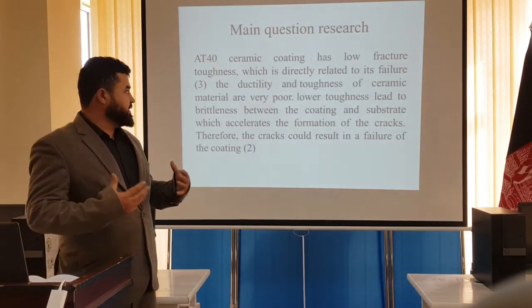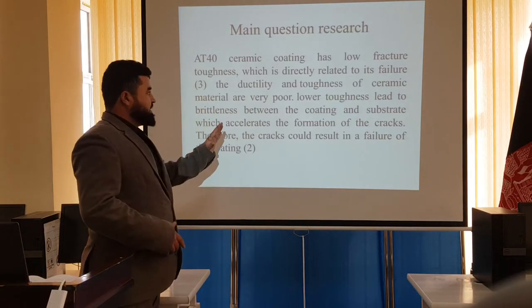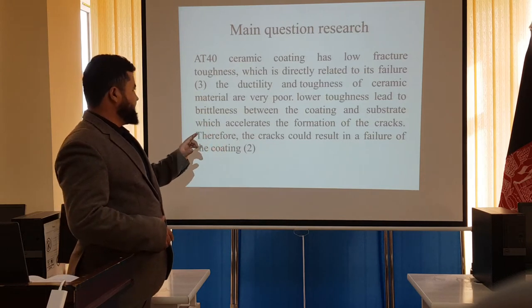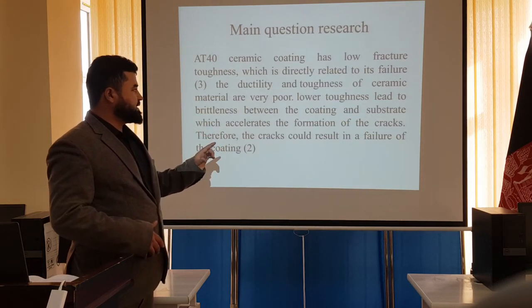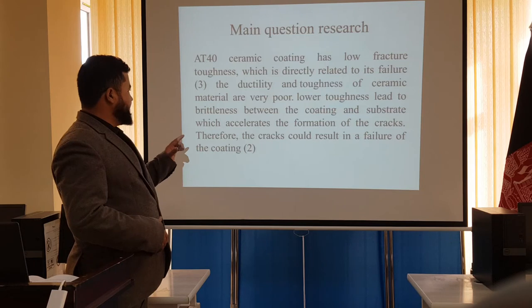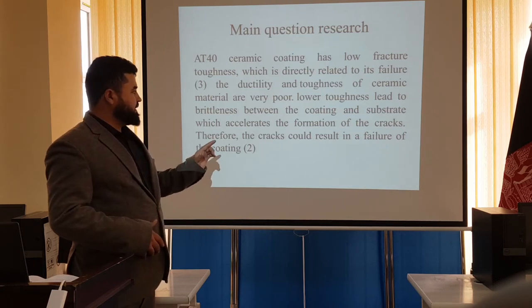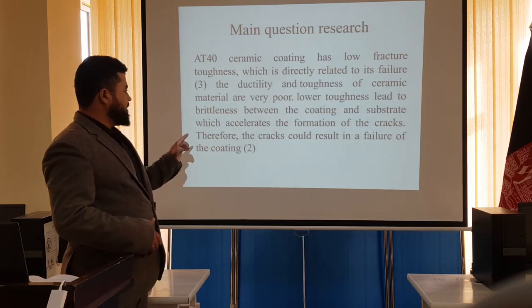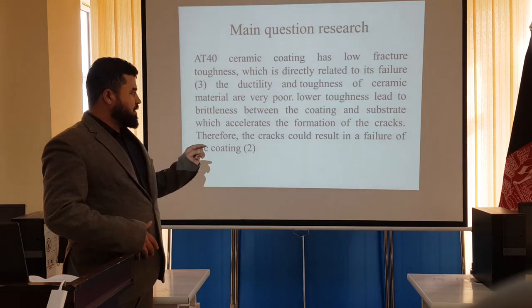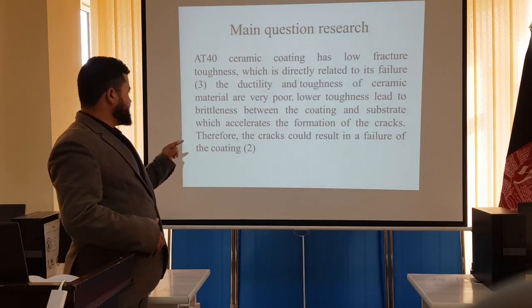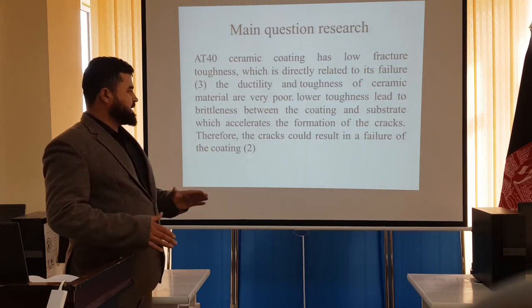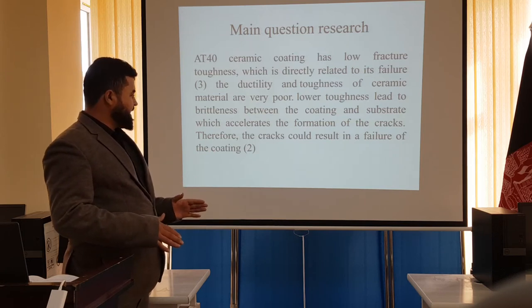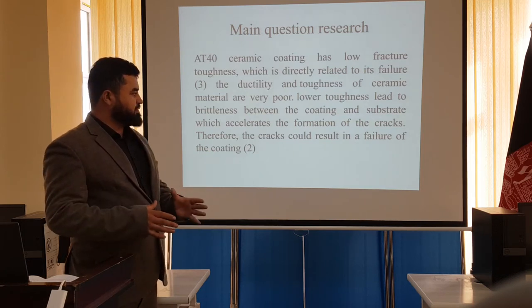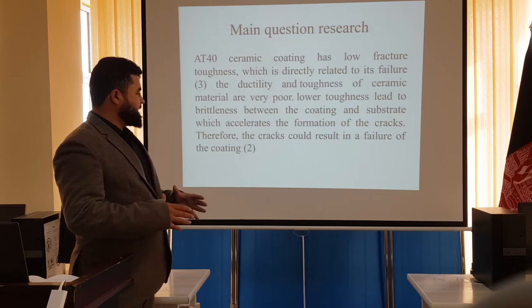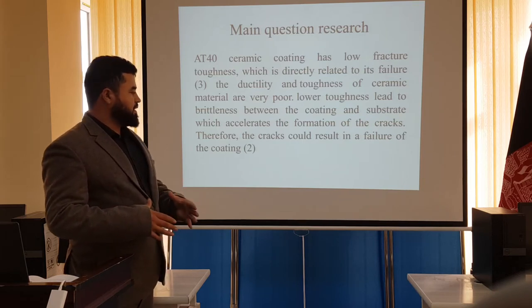The main question here: AT40 ceramic has a low fracture toughness, which is directly related to failure. The ductility and toughness of ceramic material are very poor. Lower toughness leads to breakage between the coating and substrate, which accelerates the formation of cracks, and therefore the cracks could result in the failure of the coating.